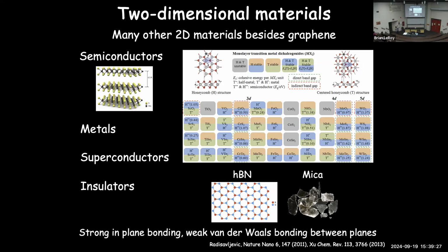There are also many naturally occurring materials. Here's an example of mica, which you can find around Tucson. If you go around on the mountains and look around, you'll find lots of pieces of mica lying around, which is another one of these two-dimensional materials, which is naturally occurring. And the key component is down here at the bottom. For all of these two-dimensional materials, you have very strong in-plane bonds, so the boron-nitrogen bonds here, the carbon bonds in plane are strong, and you have weak van der Waals bonds out of plane. And that's what allows us to take these bulk crystals like mica or graphite and turn them into these two-dimensional materials.